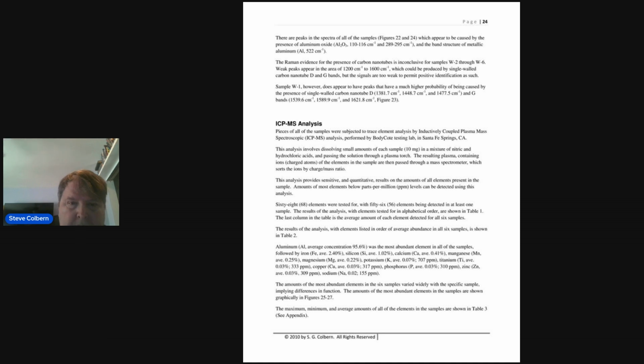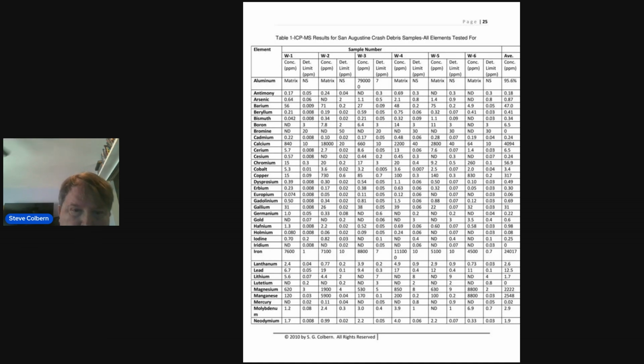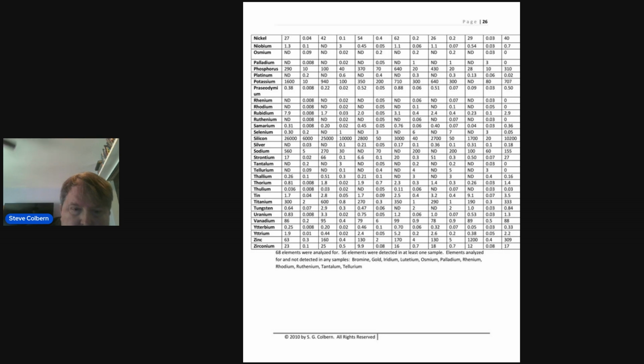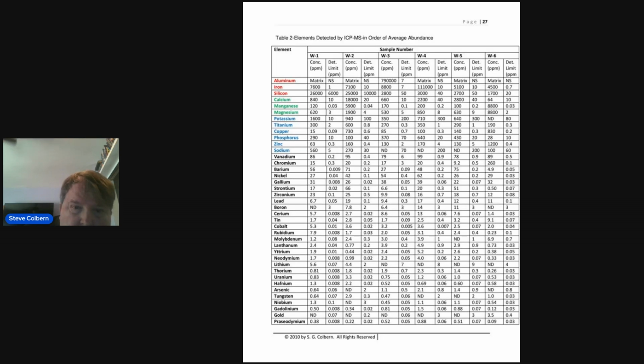Next page. Yeah, here it is by sample, and it's more instructive to do it by average abundance. Next page. Next page. Here we go. So in all the samples, aluminum was the matrix material, the number one material, followed by iron. 7,600 ppm of iron in W1, and W2 had 7,100, 8,800 in W3. Yeah, W4 had the most iron with 111,000 ppm. That's like 11%, I believe.